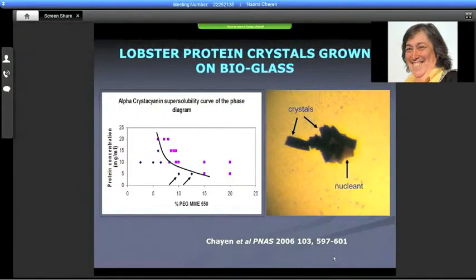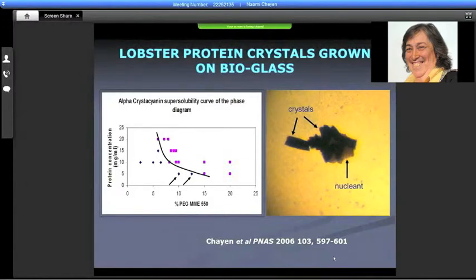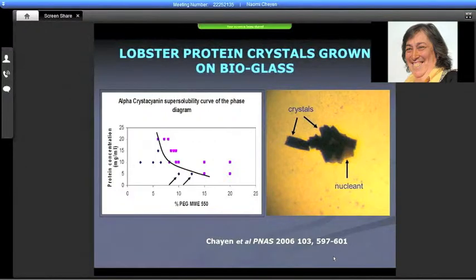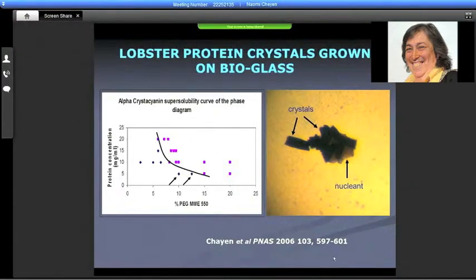How do you find the metastable zone? People are doing this all the time without realizing it. When they get a hit, for optimization and fine-tuning they go a little above or below the hit conditions — doing say five, six, or ten experiments above and below the hit. Where you get too many crystals, that's oversaturated. Where you get no crystals, just at that point, that is your metastable. So you don't want to go too low into the undersaturated where nothing will happen. People do this for seeding all the time and just don't realize the nucleant should go in those same conditions.